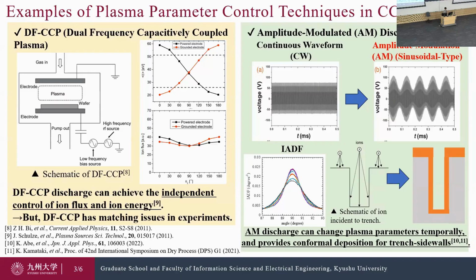Next, in contrast to conventional continuous wave, CW, discharge with radio frequency voltage, amplitude modulated, AM, discharge, where the voltage amplitude is varied over time, allows plasma parameters such as ion incidence angle to change over time in response to voltage amplitude variations. This enables conformal thin film deposition on the sidewall of trench structures in TEOS PCVD.